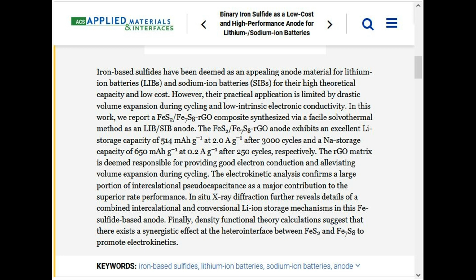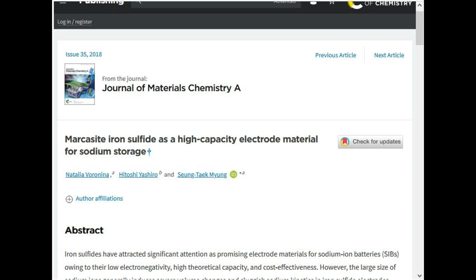The RGO matrix is deemed responsible for providing good electron conduction and alleviating volume expansion during cycling. The electrokinetic analysis confirms a large portion of intercalational pseudocapacitance as a major contribution to the superior rate performance. In situ X-ray diffraction further reveals details of combined intercalational and conversional Li-ion storage mechanisms in this Fe sulfide-based anode. Finally, density functional theory calculations suggest that there exists a synergistic effect at the hetero-interface between FeS2 and Fe7S8 to promote electrokinetics. Marcasite iron sulfide as a high-capacity electrode material for sodium storage.